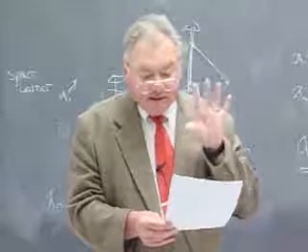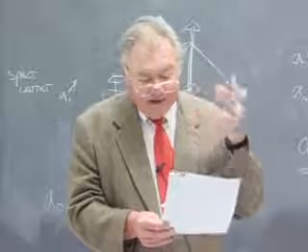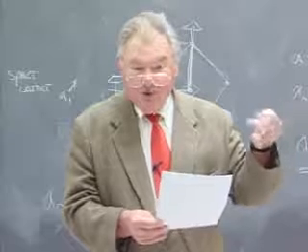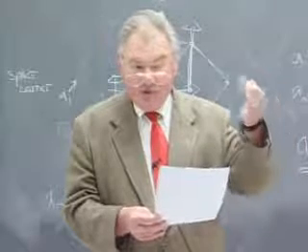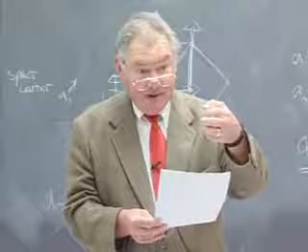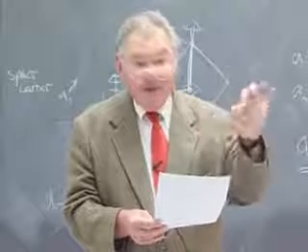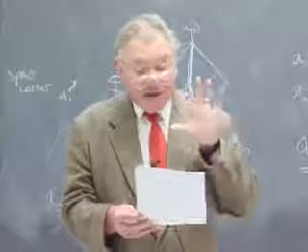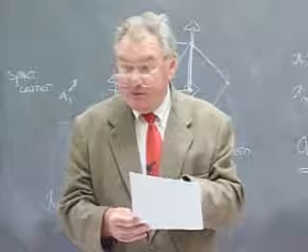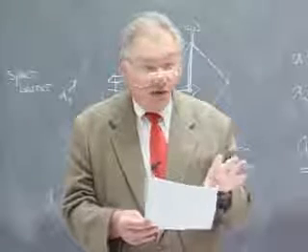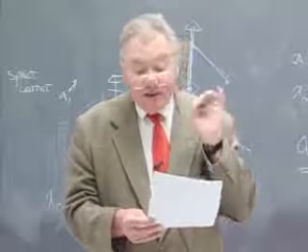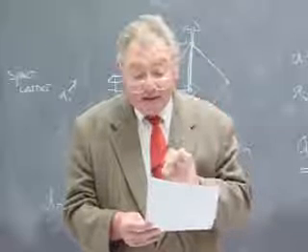So any one of the point groups that differs from the 10 two-dimensional symmetries, namely 1, 2, 3, 4, 6, m, 2mm, 3m, 4mm, and 6mm, any symmetry that you get by adding inversion to those two-dimensional point groups is automatically going to be happy in the space lattices that we've derived to this point. So we have done an enormous fraction of the work that's required to derive space lattices and the space groups as well.